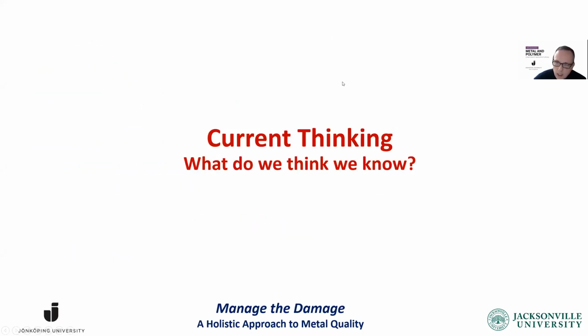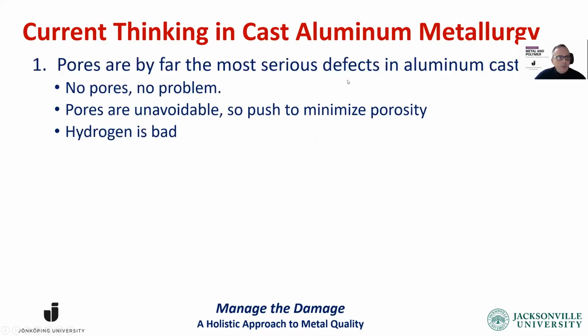What is the current thinking in our aluminum foundry industry? What do we think we know? First of all, there's a general consensus that the pores are by far the most serious defects in aluminum castings. But if there are no pores, life is good. And pores are mostly unavoidable. So the best we can do is to minimize pores. And one of the number one enemies is hydrogen. Get hydrogen out of there.